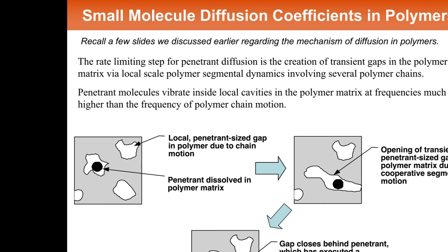I mean, look at this. This is out of a variety of penetrants and a variety of polymers. And these are the data for glassy polymers at the time, and these are the data for rubbery polymers. And that front factor in the diffusion coefficient is very strongly correlated with the activation energy. What does that mean in a practical sense? Well, I can take that relationship and put it into the Arrhenius expression I showed you on the first slide. And you get this expression.